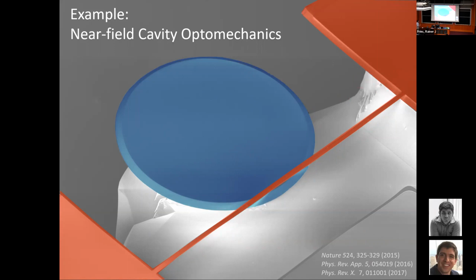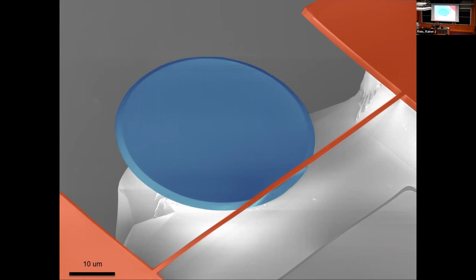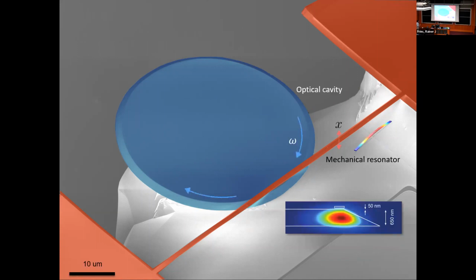And it's placed, and this is hard, in the evanescent near field of a whispering gallery mode resonator. The blue here is just a piece of glass that's been wrapped in a loop, essentially an optical waveguide wrapped in a loop, and it supports optical modes by total internal reflection around the periphery. A little bit of the mode leaks out with an evanescent decay length around 100 nanometers, but if you're really good at fab, you can heterogeneously integrate this beam within the evanescent near field. And that allows you to very sensitively measure the displacement of this mechanical oscillator.